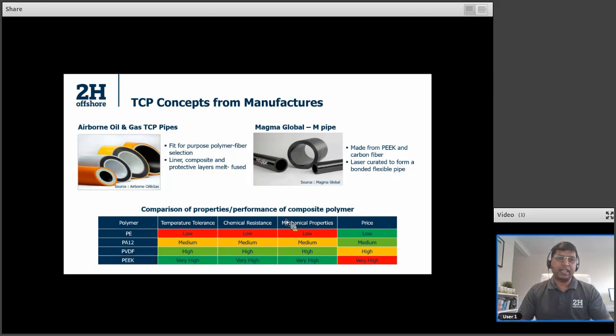Polyethylene has a very low tolerance. It's qualified up to 65 degrees. PA12 is qualified up to 80 degrees. PVDF can go as far as 121 degrees for TCPs. And PEEK can provide higher performance in excess of 130 degrees.